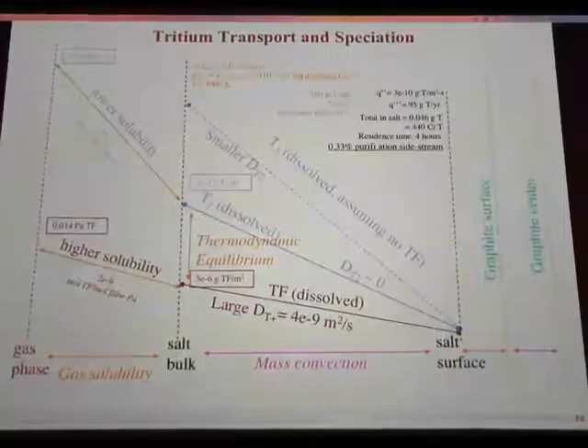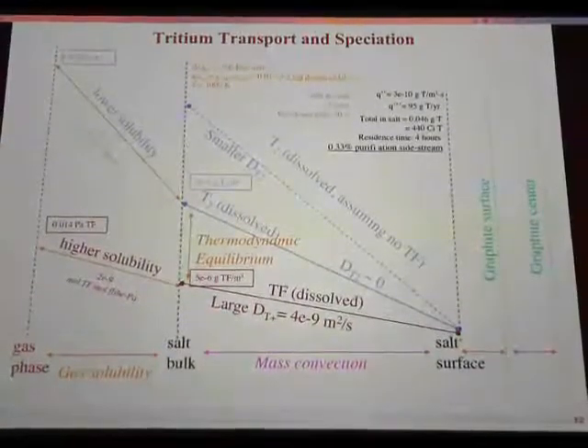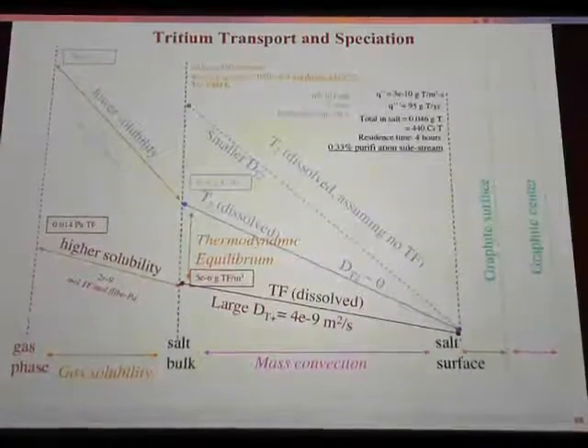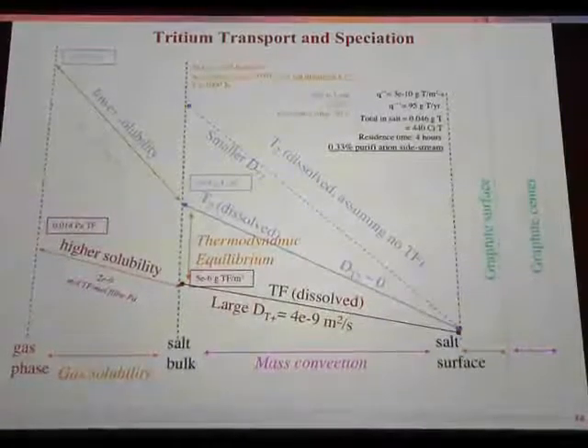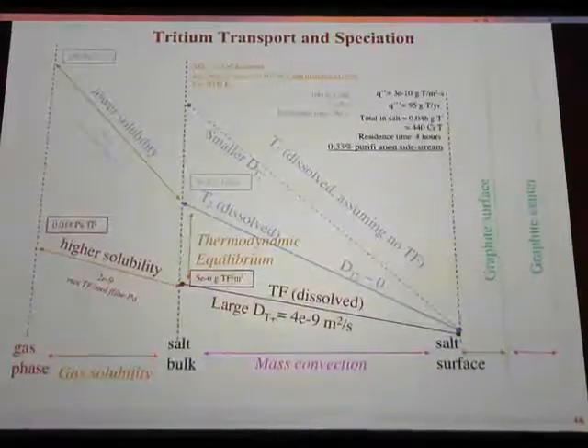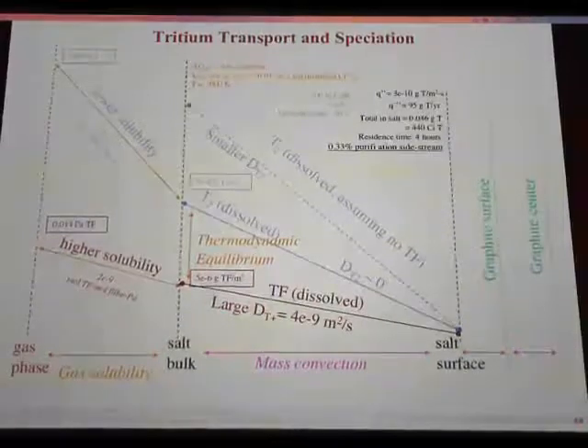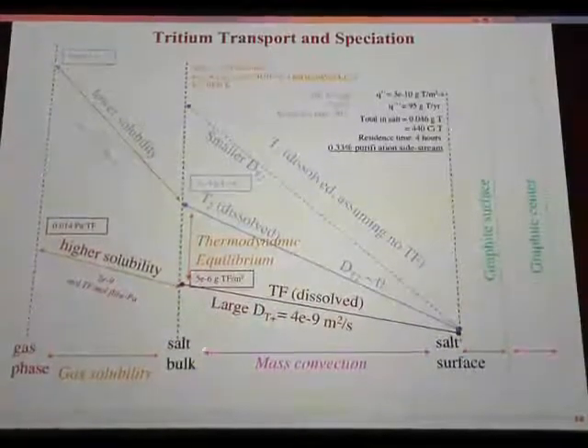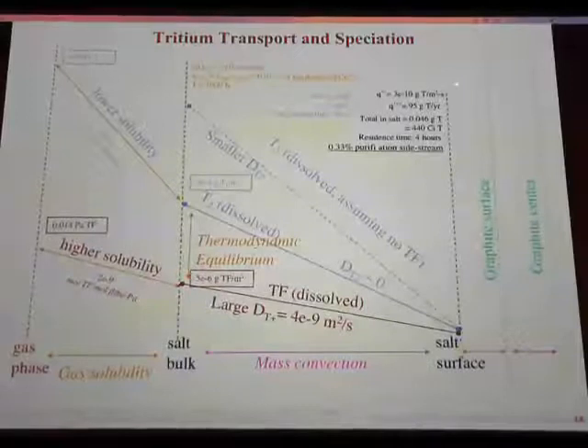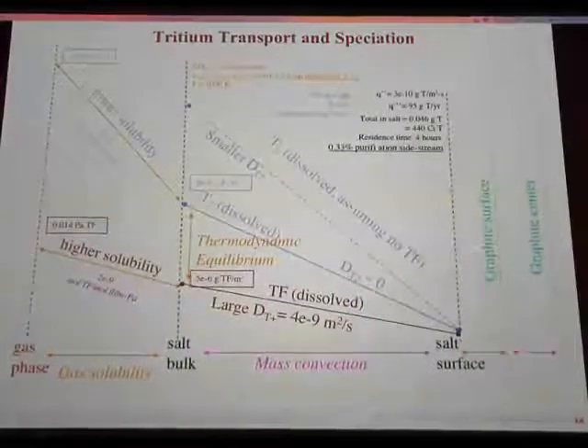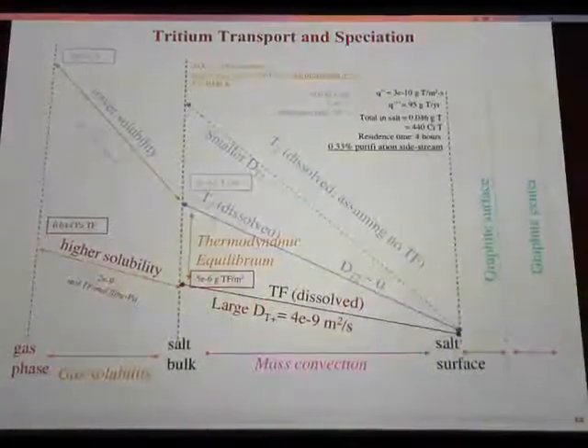It's lower than any data that we have. So that means that we need data at low partial pressure. Most data is at 1,000 Pascal and up. So that's where, and then you can go and calculate the tritium inventory, and that's where those numbers came from that I showed you before.